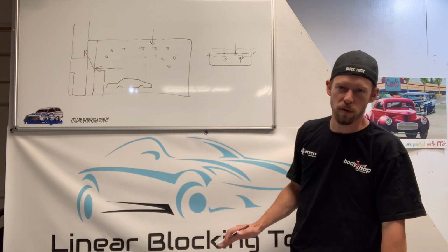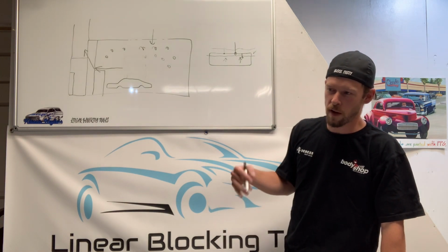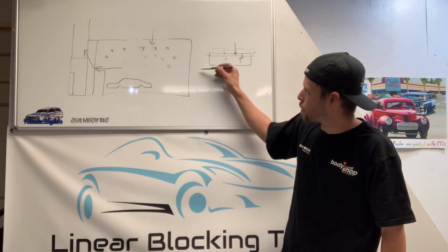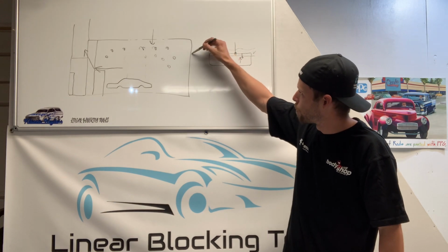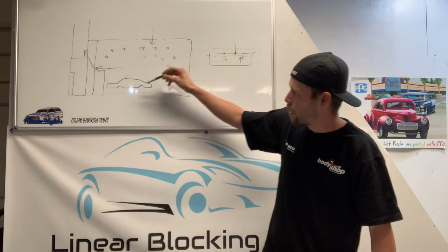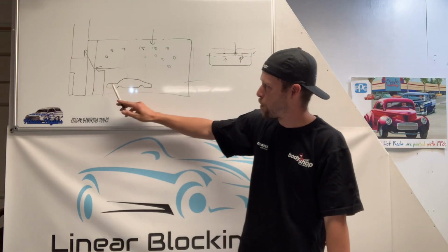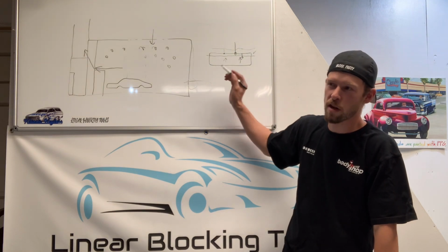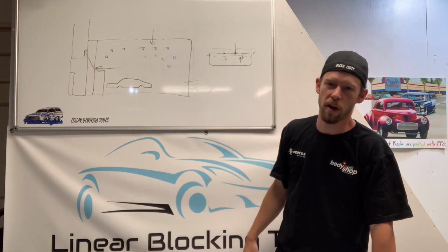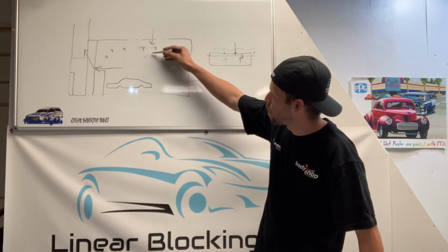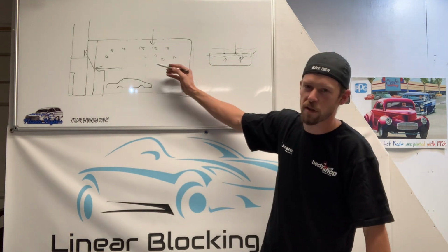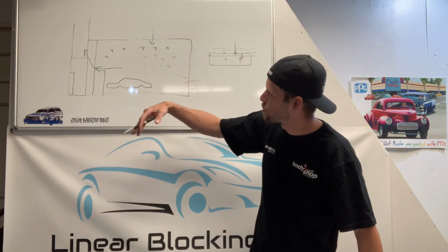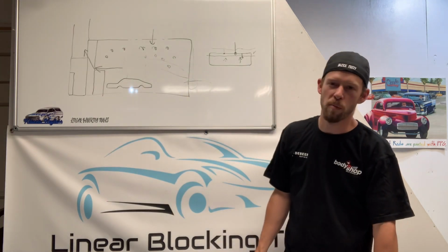Another thing that I do to avoid this is after I've cleared and I've let the booth run for 2 hours, whatever the number is, I always open the doors. So in the booth that we spray in, we've got the drive-through doors here, and then I'll open my paint room door and my paint booth door, and you can even put just a little 20-inch box fan or something right there, just anything to keep a slight bit of air moving, because for this whole process to happen takes quite a while of very still air, and all you need to do is just keep some air moving through here and let the solvents slowly get out of the booth.